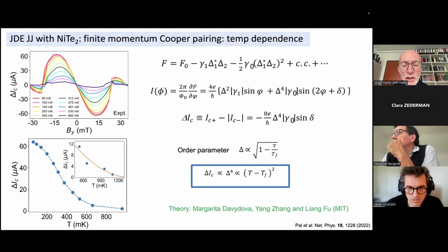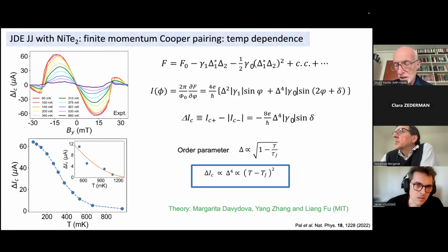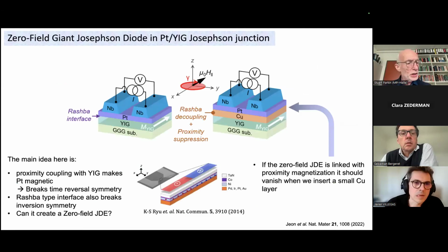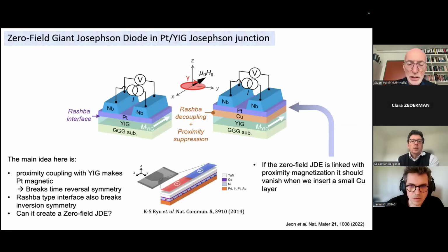So we think this is very compelling evidence for this concept of finite momentum pairing, similar to what I discussed earlier, but now not in a ferromagnet, but through the field-induced splitting of the topological surface states. And this is where the finite momentum comes from. So now I want to, in the last few moments, mention briefly some other experiments. In the last 2 or 3 years, we've explored a wide range of different materials.